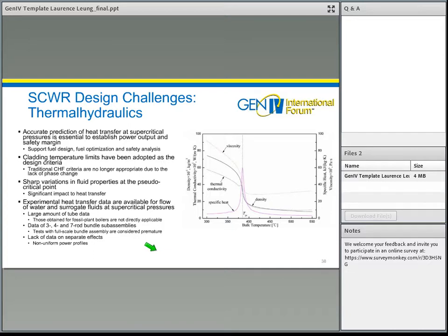So the limit that we use is always based on the cladding temperature or the fuel temperature as the criteria. So we need to predict the heat transfer accurately because of the sharp temperature or property variation along the pseudocritical point. This figure shows the density variation, thermal conductivity, specific heat and viscosity as a function of bulk fluid temperature. This is the pseudocritical point in this area.